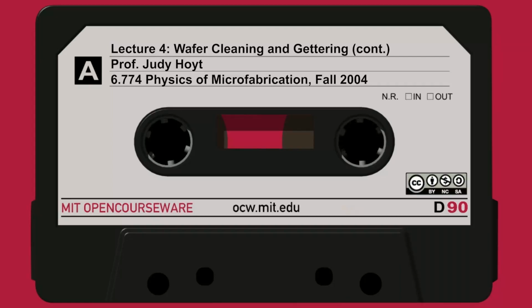So slide 21 qualitatively lists a series of explanations of why N+ silicon is a good getter. It's a good trapping area. We just saw the statistics of the acceptor and donor levels versus doping from Shockley's paper that is consistent with that. There's also an ion pairing model: a large atom like gold, and gold is very large, might want to pair with a small atom like phosphorus and form some kind of AuP complex, because this minimizes strain.